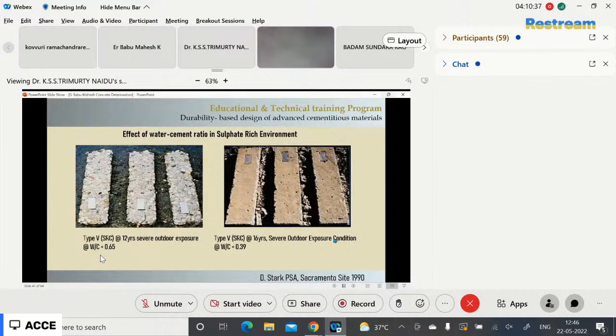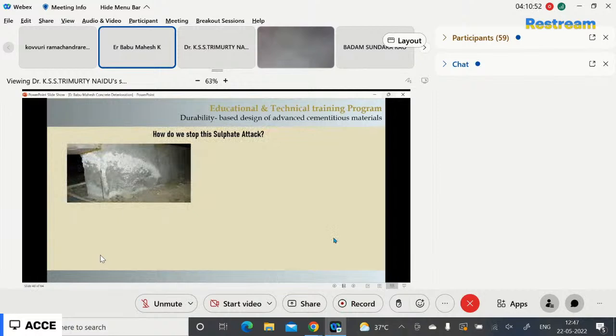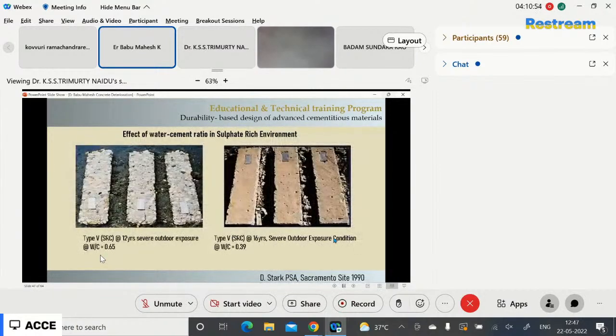So, effect of water cement ratio in the sulfate rich environment. Type 5 cement, that means SRC cement, has been used for making these concrete beams. They have been placed 12 years in outdoor conditions, and we have to determine the sulfate attack on these concrete beams.